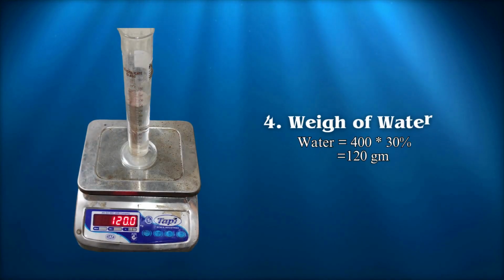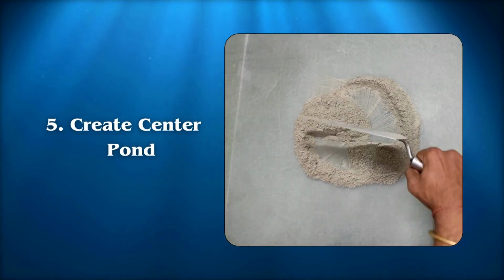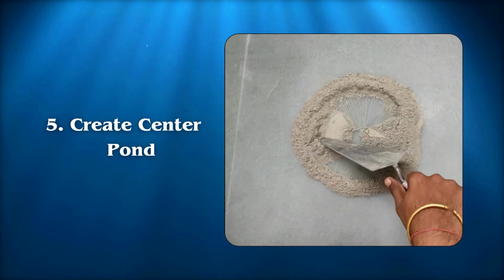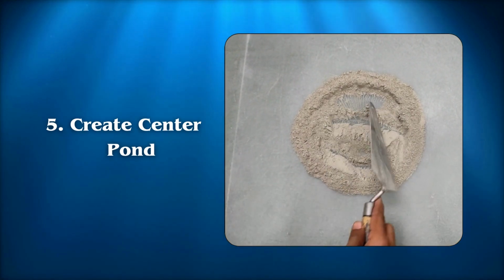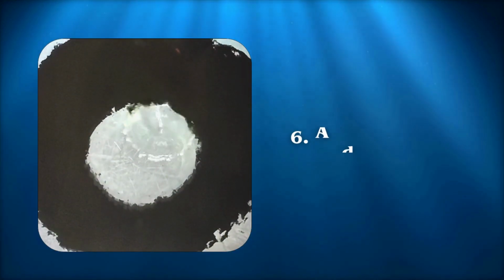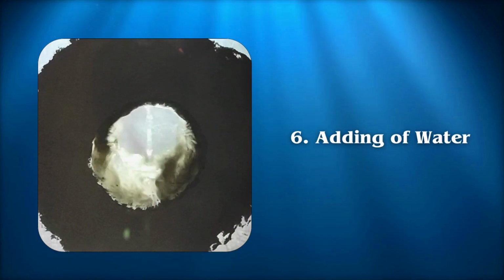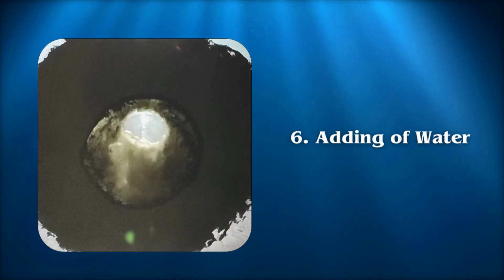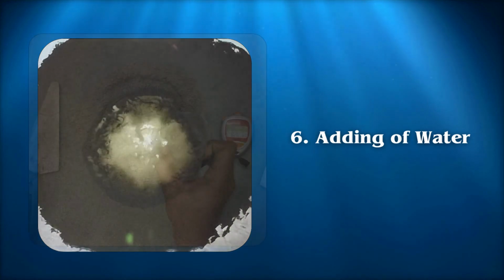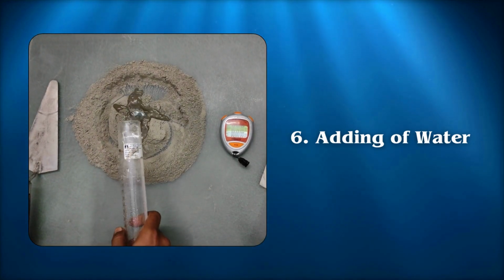Next, weigh the required quantity of potable or distilled water by percentage of quantity of cement. For example, we take 30%. It's crucial to maintain precise measurements during this step. Then create a central pond within the dry cement. Gradually add the pre-weighed water to the cement and thoroughly mix the two components until you achieve a consistent paste.